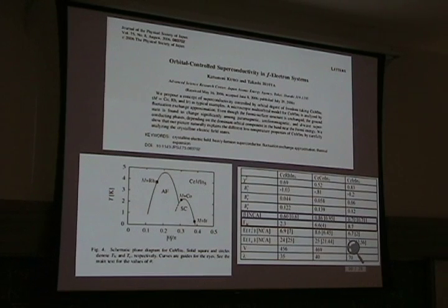But it's interesting to know that when you consider both orbital and spin degrees of freedom of that lower crystal field state, you can tune your ground state from antiferromagnet to superconductor by controlling the competition between the orbital fluctuation and the spin fluctuation given by that state.